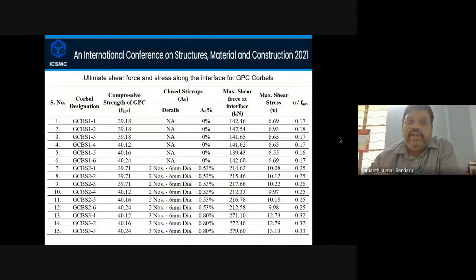These are the ultimate shear forces and the stresses along the interface of the GPC corbels, where the maximum shear force is noted. You can also observe that the shear stress to compressive stress ratio is about 15%, and when the reinforcement is there, it is about 25%.